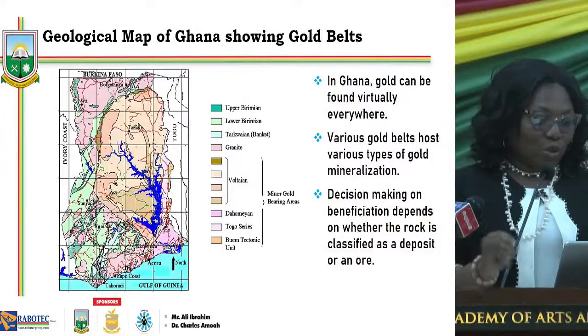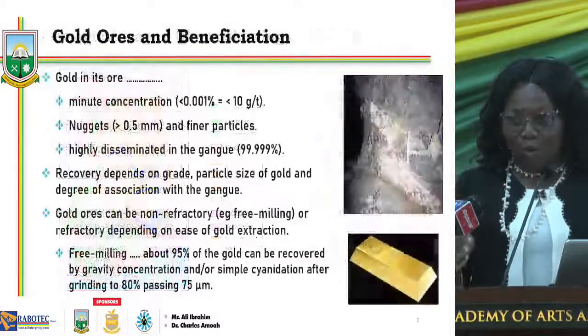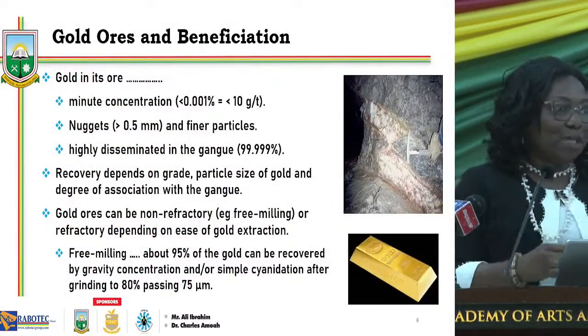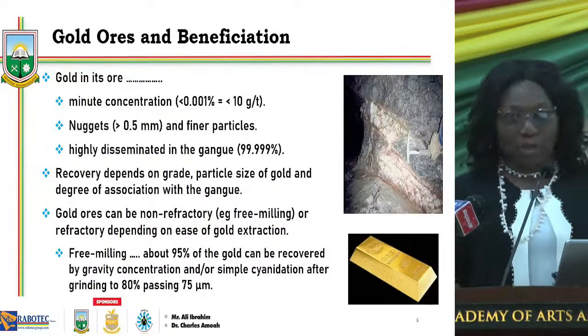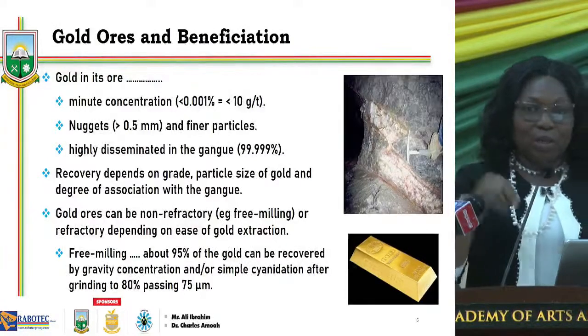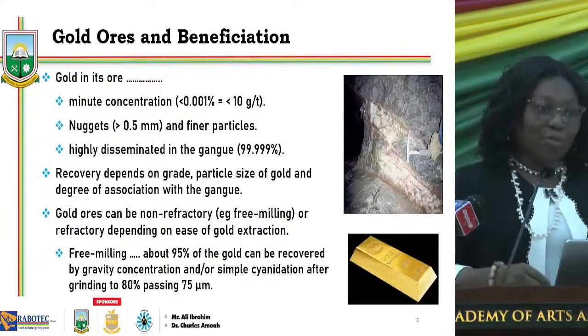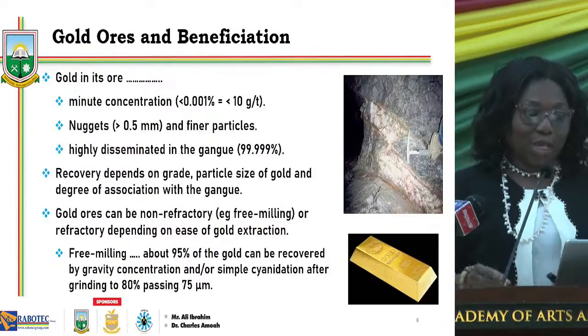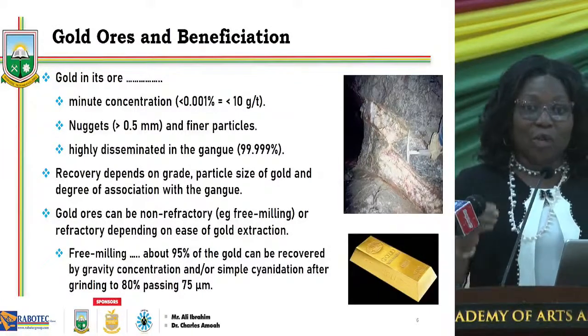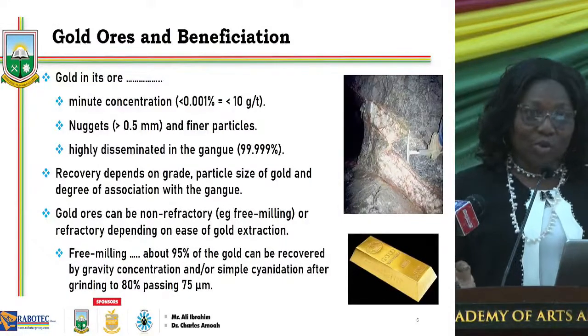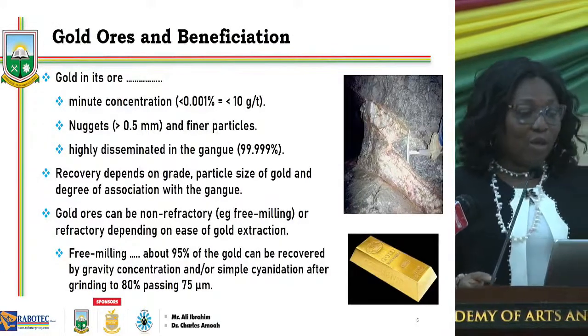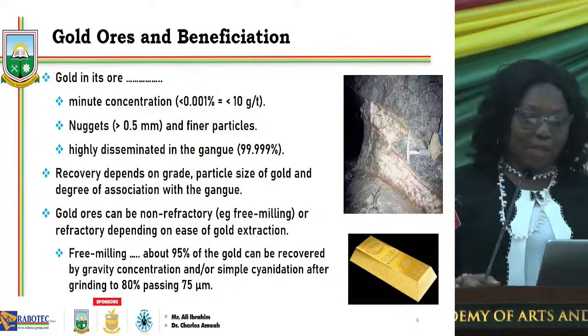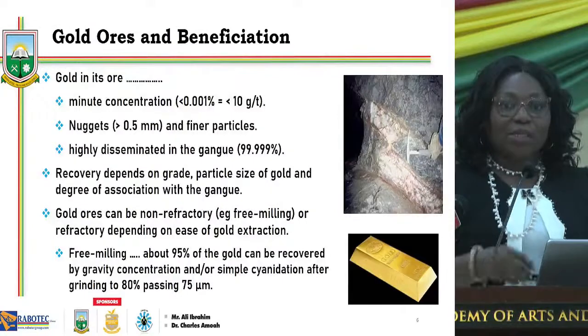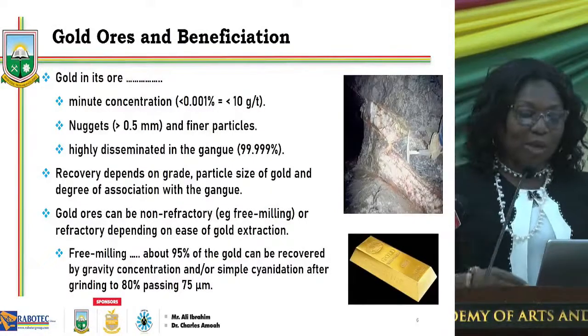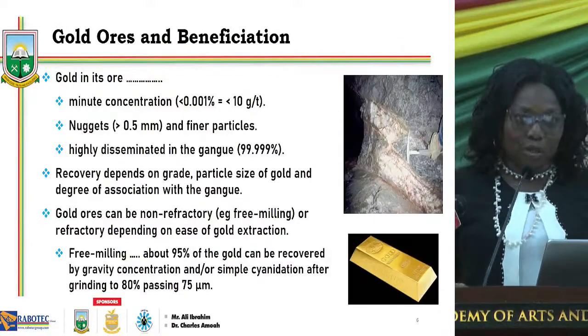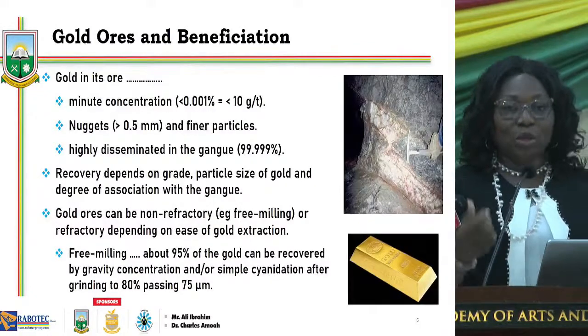So when we talk about gold ore, the concentration of gold in the ore is so small, such that it is expressed in parts per million or gram per ton. So if we say the grade of gold ore is 10 grams per ton, we are talking about 10 parts of gold in a million parts of unwanted materials. In the gold community, if you talk about 10 grams per ton, it is high grade, very high grade. But if we try to express it in percentage, we are going to have 0.001%, and that looks like nothing. So this concentration of gold, it's spread all through the unwanted materials. And we are talking about 99.999% of unwanted materials.